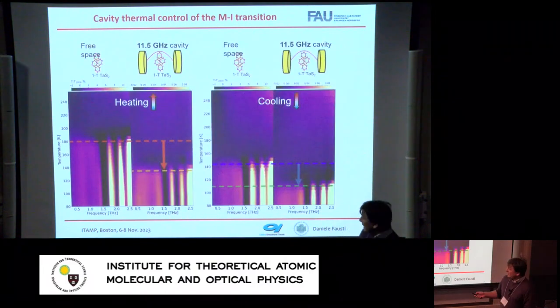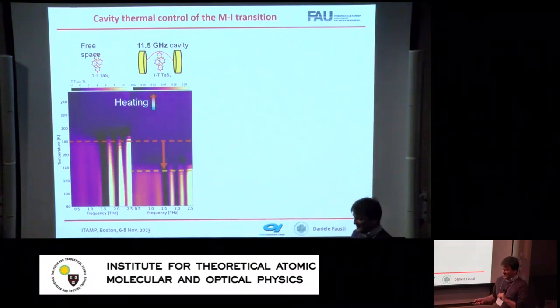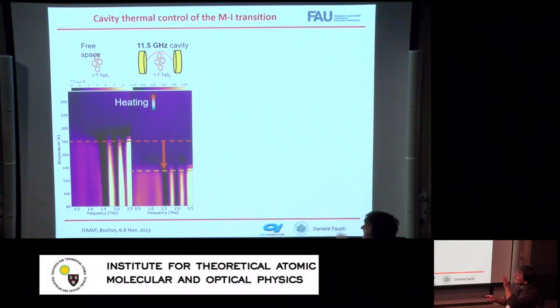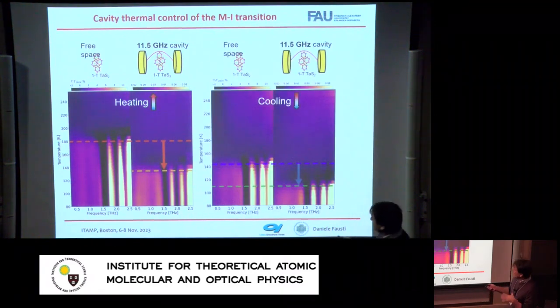The published work you can find in the published paper, so I can go very fast here. Essentially, we realized that if we place the sample in a very large cavity, we can change the apparent phase transition temperature. I say apparent in the sense that this is the phase transition temperature of the support of the sample. And it's a real shift in the sense that it's a static shift that I can observe.